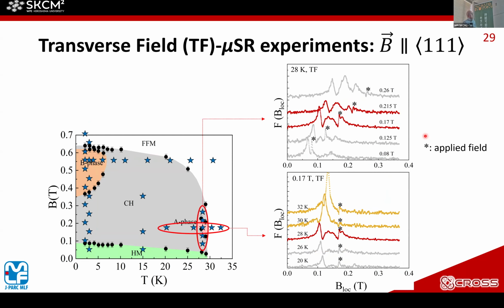And also, here we show the field distribution of data around the A phase. Around the A phase, the internal field distribution is completely different from the conical phase, like this, which is due to the skyrmion lattice. And this is the temperature dependence of the distribution. The skyrmion lattice has a special distribution.